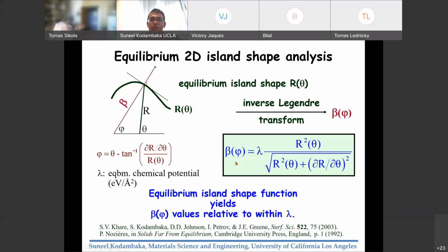And if you were to do this for two-dimensional islands, the step energy is given by this expression, where R of theta is the shape function of the island of interest, and it's the equilibrium island shape. And lambda is the equilibrium chemical potential per unit area. Okay. Typically, when you do Wulff plots, you get this relation, but without the lambda. And without the lambda, you do not have any absolute values. All you know is how the step energies change with orientation, but not by how much.